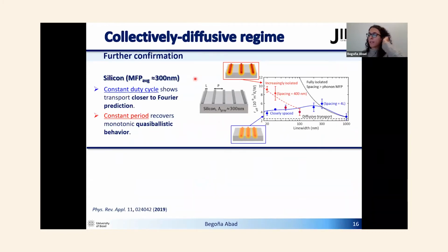In order to corroborate this, we did another experiment, which was based not only on keeping a constant duty cycle. This is the blue line, where you keep the same proportion of nickel in your nanograting, so that as you reduce the nickel line width, the period is also reduced. And this is when we see the turnaround. But we kept the period constant. That is, when you reduce the line width, the lines are more and more isolated. And here we could see that doing that, keeping the period constant, recovers the monotonic quasi-ballistic behavior.